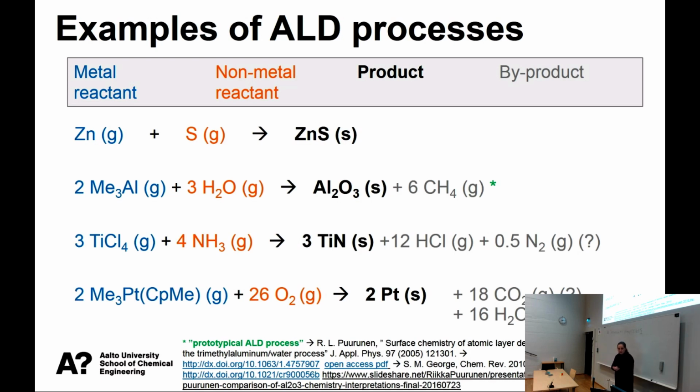And then there is still a different type to grow platinum films. This is something that was developed at the University of Helsinki a bit more than 10 years ago and has become very popular in the world. Noble metal films by oxidizing, simply burning off the ligands. Because the noble metals want to be metallic, they still make the metal films even if you oxidize them. And whether that's purely burning and giving CO2 and water or something else might depend on the reaction conditions a little bit.